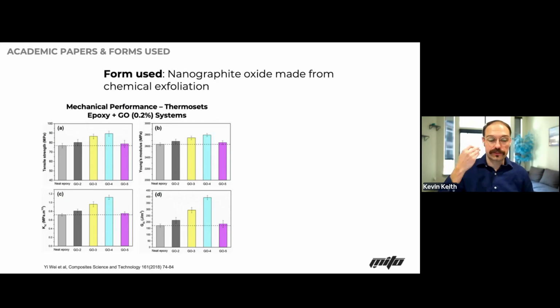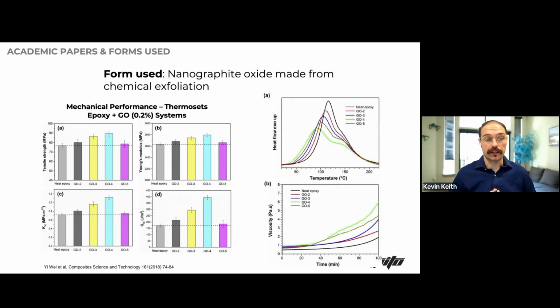So going through a couple of different papers, as well as the forms that were used. Here we have a system that's used with thermosets. It's a nanographite oxide made from a chemical exfoliation. And so what they did is they sonicated into this thermoset at 0.2% by weight. This graphite oxide was a nano powder. And so by the time they got it integrated, you can see here that as you start increasing your GO concentration, you get more and more, but then at some point, it's going to start very much degrading. At the 0.4%, you generally see a much higher, but even then, you're only getting maybe about a 10% increase for that amount of loading.